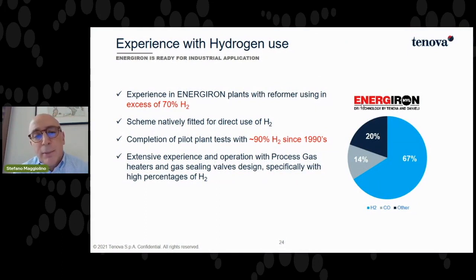And most of all, we have the experience. Just imagine that in a plant with the reformer in our scheme, we already have 70% of hydrogen. So moving from 70% to 100% for us is not a big change. Additionally, we have the perfect scheme for the use of hydrogen by using a process gas heater. In the 90s, we've done campaigns with use of up to 90% of hydrogen, and then we have extensive experience with the process gas heater and sealing gas valves that are necessary for the use of hydrogen.